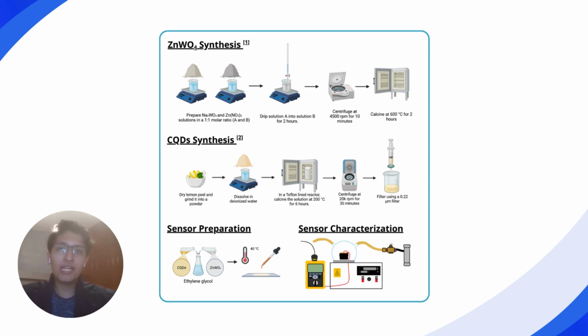The methodology followed is a combination of two reported synthesis methods. On one hand, we have the zinc tungstate reported by Shiley Young that consists in a co-precipitation technique of sodium tungstate and zinc nitrate in a 1:1 molar ratio. On the other hand, we have a slightly modified carbon quantum dot synthesis reported by Jayakumar A, where lemon peel is dried, grinded, and dissolved for its use in a hydrothermal synthesis. The obtained solution is centrifuged and filtered, so only a carbon quantum dot solution remains with no other organic matter.